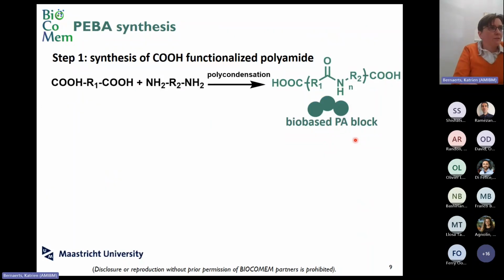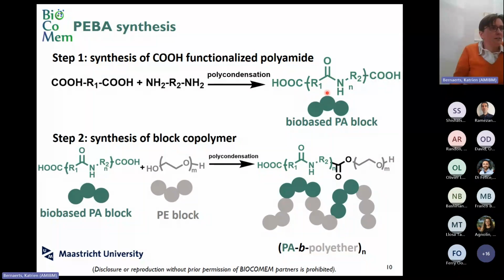For the PEBA synthesis, we use a two-step process. In the first step, we make a polyamide that has carboxylic acid end groups. The polyamide is obtained by combining typically a diacid and a diamine via a polycondensation process. And as Juan already said, we target the use of bio-based building blocks. In the second step, we combine this diacid functionalized polyamide block with a polyether block like polyethylene oxide, and the polyether block is diol functionalized. So we combine acid and alcohol with the formation of an ester link between the amide and the ether blocks. And those blocks are alternating each other.